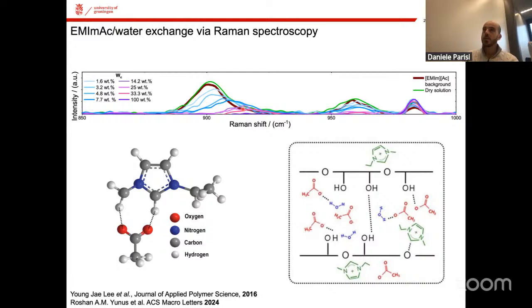This is because at some point the acetate will start interacting with water, as it is also shown in this cartoon here. And water is a much smaller molecule compared to the cation. So this is basically what we are seeing here. Eventually, when we have 100% of water, there is no signal anymore. So it's basically the same as the background, meaning that we are not able to detect ionic liquid anymore. So we cannot say that it's not there absolutely, but certainly not in an amount that is detectable experimentally.